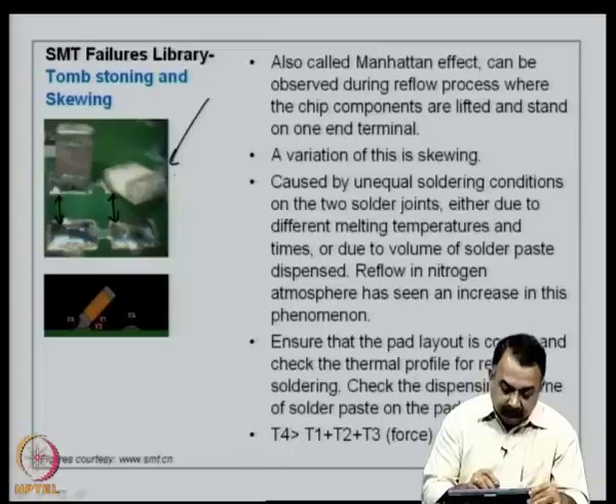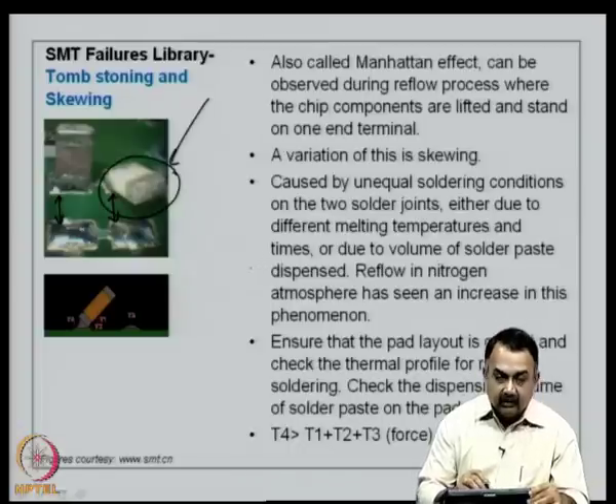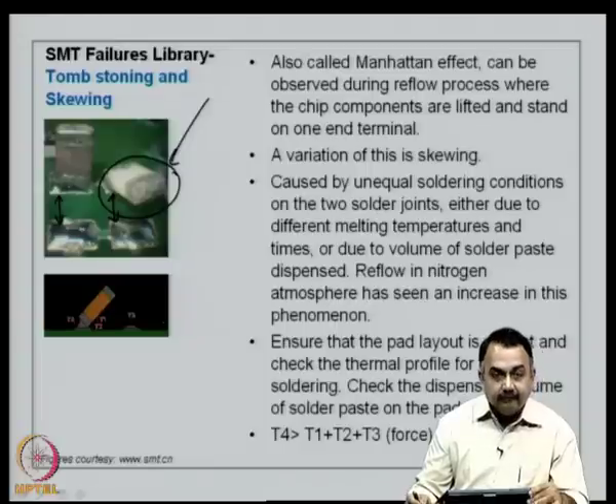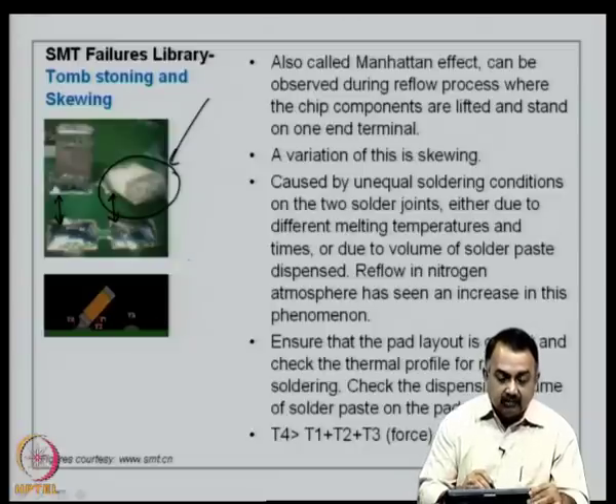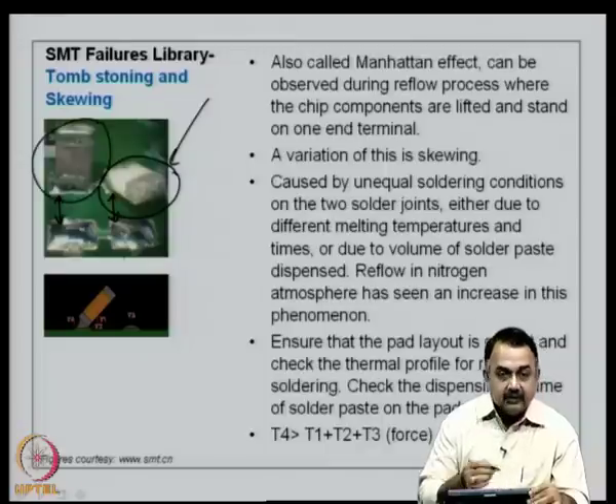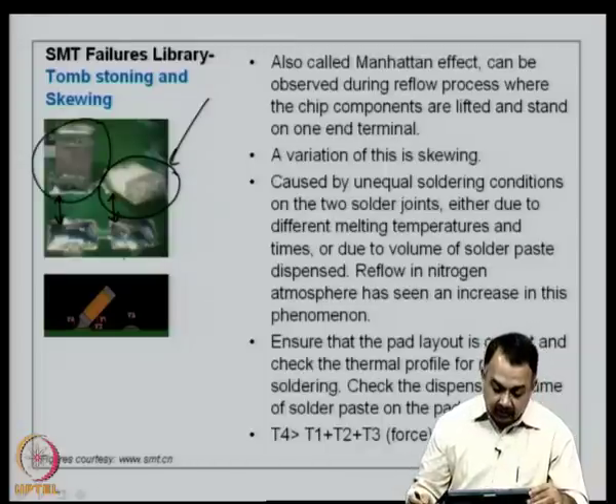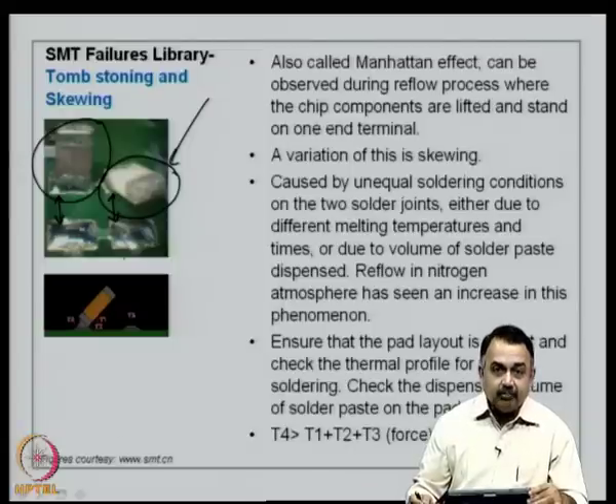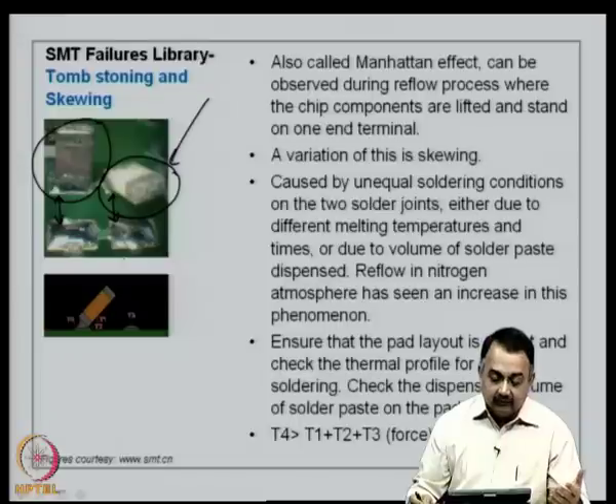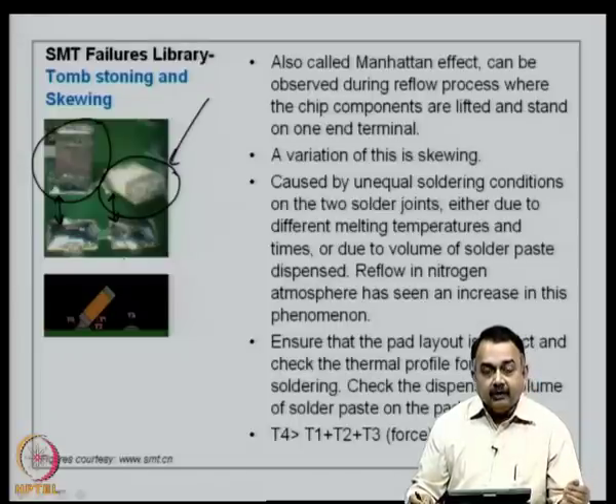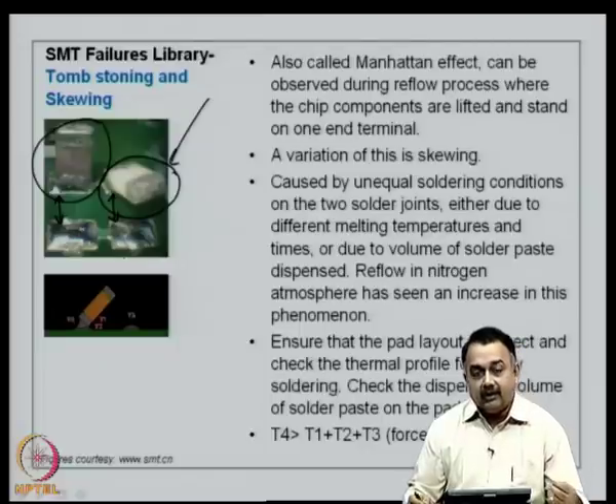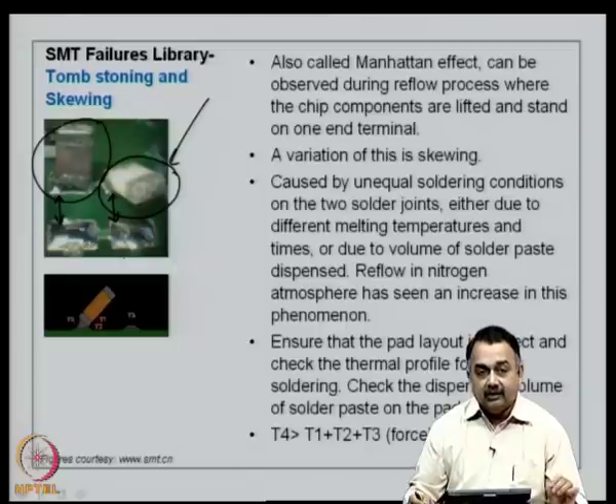Now, in this picture you can see that one component has lifted from the pad of the printed circuit board, and then it has skewed a bit, and in the other case you can see that it has lifted fully and it is standing as a tombstone, hence the name tombstoning effect or skewing effect. Now, this can be observed during the reflow process, where the chip components are lifted and stand on one end of the terminal, and a variation of this, as I told you, is the skewing that you see. And how is this caused? It is caused by unequal soldering conditions on the two solder joints that the chip component is supposed to be placed on and then soldered perfectly.